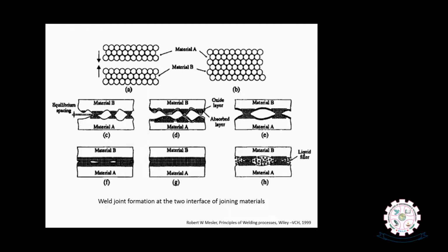The basic principle of welding is this: when we bring two surfaces of any material together, if we don't find valleys and peaks, or the presence of oxide layers, absorbed layers or any contamination between the two surfaces, then all the atoms present at both surfaces, if they come close together to a distance called the interatomic equilibrium distance, form strong bonds. If we are able to bring all the atoms at the surfaces to such interatomic equilibrium distance, then a perfect metallurgical continuity will be established. That is what we theoretically call welding.